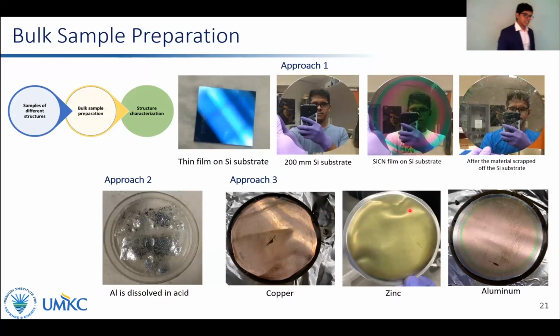One of the challenging parts in the structural characterization of these materials is the sample requirements for experimental techniques. In the factorial design experiment, we fabricated thin films up to a thickness of 200 nanometers on 1.5 by 1.5 centimeter silicon wafers. The sample collected on these surfaces was approximately a few micrograms. But for NMR and neutron diffraction, we required 30 milligrams or 150 milligrams of sample, which was a huge challenge. So for the synthesis of bulk materials, we developed 3 different approaches.